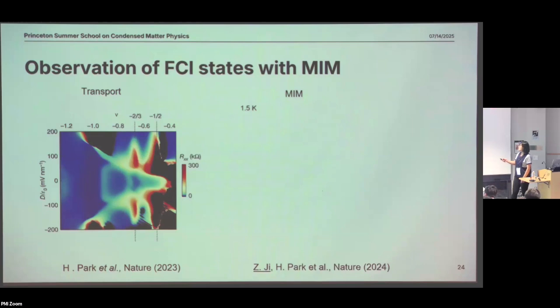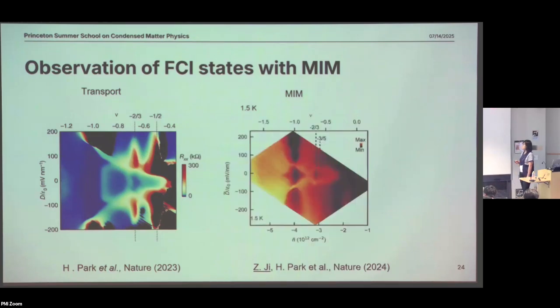So we also tried to use MIM to look at this particular system. And the result looks like this. Here the maximum means more conductive and the minimum means more insulating. As you can see, near nu equals minus 1, and when the displacement field is small, the y-axis is displacement field, the x-axis is the carrier density or the doping, then here there's an insulating regime. And similarly, at nu equals minus 2/3 and nu equals minus 3/5, there were two blobs of insulating regimes. So that shows good correspondence with the Rxx that they measured in the transport.